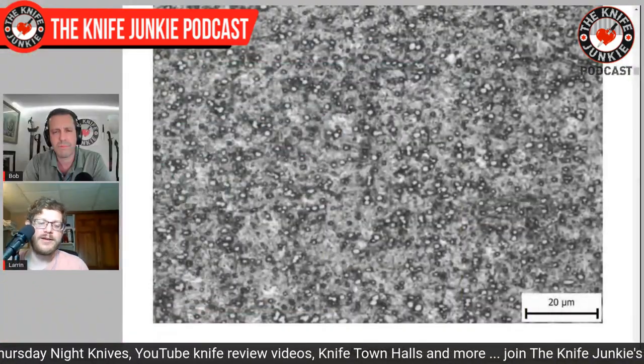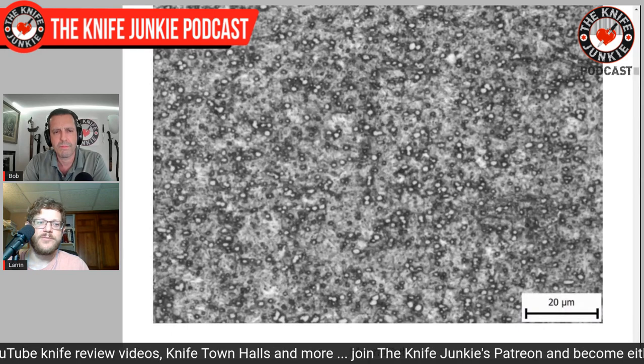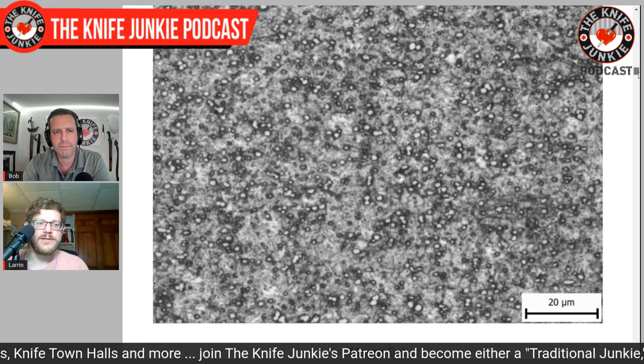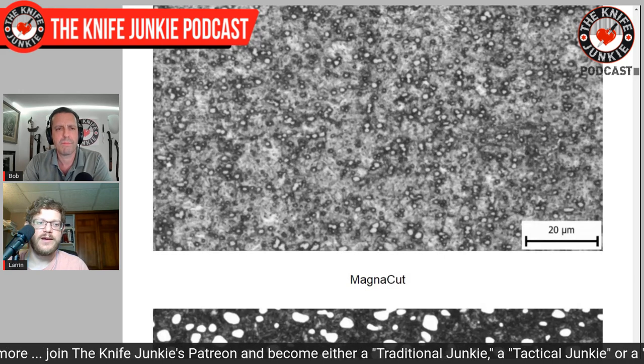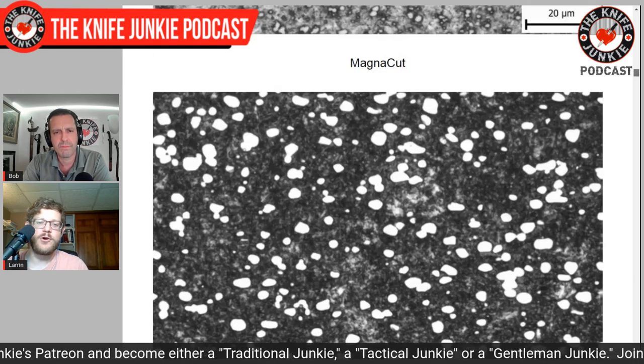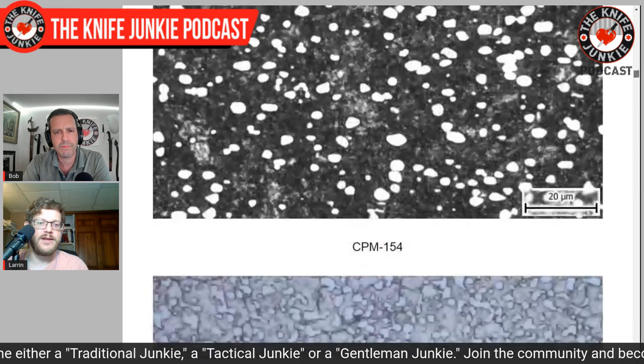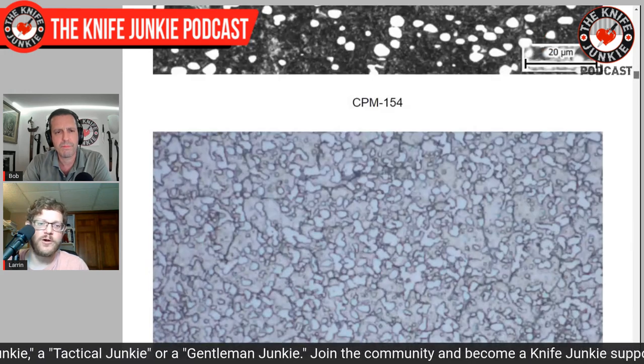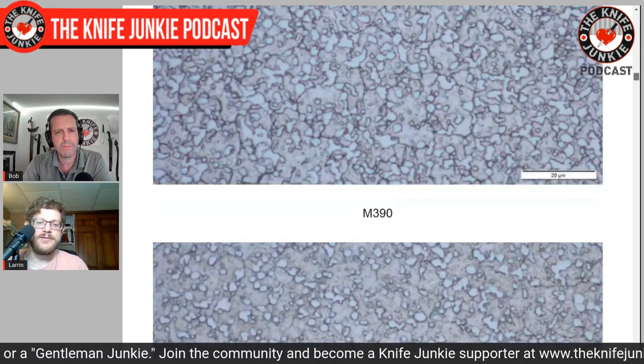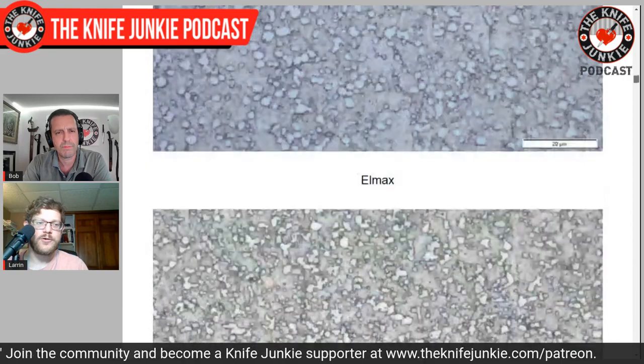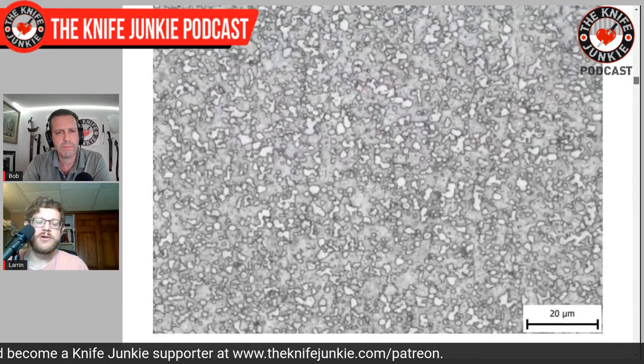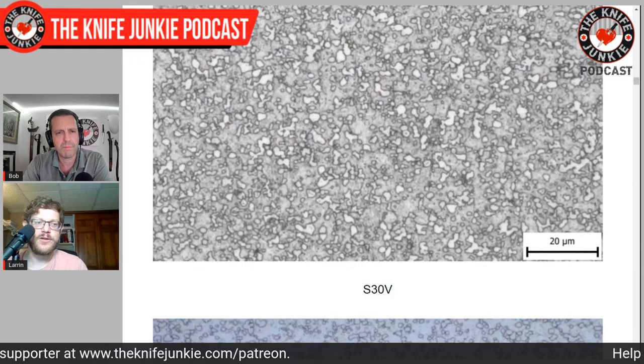In a tool and die situation, they don't care really about corrosion generally. But in knives, we would prefer to not have to baby the knife, and we'd like it just to not rust. So I wanted to make a stainless steel that had the properties of those best non-stainless steels. And one of the jumps forward that Crucible had made with S90V and then again with S30V is they reduced the chromium content. Because steels like M390, they've got 20% chromium in them. But in terms of chromium going towards corrosion resistance, it's only about 12 or 13%, rather than the full 20.